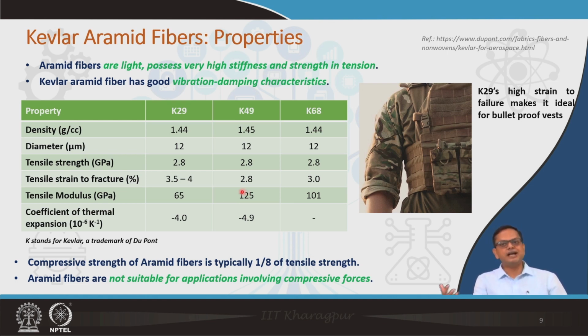Does that mean we should use that in reinforcing ballistic vests? We also have to look into the data of tensile strain to fracture. In this case, you can see the tensile strain to fracture is higher in K29. That means, before the fiber tears off or fails, it undergoes more tensile straining before fracture. Okay. So, obviously, K29 should be preferred in making ballistic vests, even though it shows lower modulus, a very important factor. Okay. So, that is all about Kevlar or aramide fibers' strength, modulus and properties.